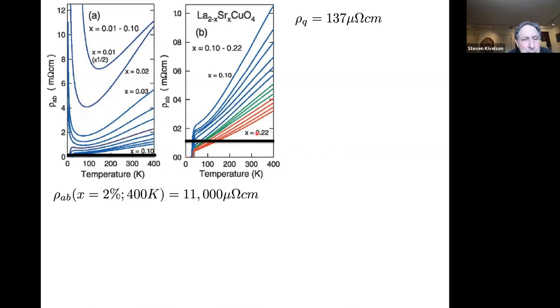Here at 2% doping, that's this sample here, we still have a regime where the resistivity is a very strongly increasing function of temperature, and yet it's got values that are improbably large, values that you can't possibly interpret in terms of quasi-particle scattering.